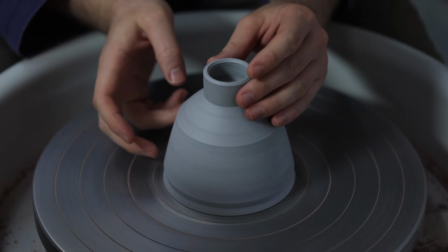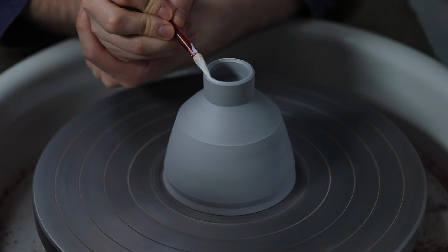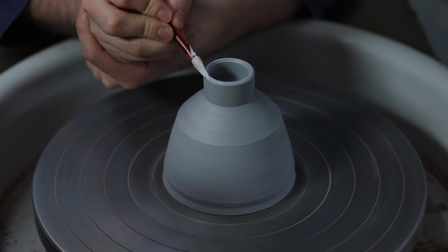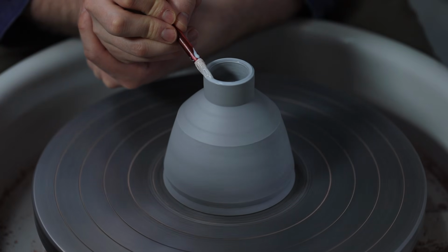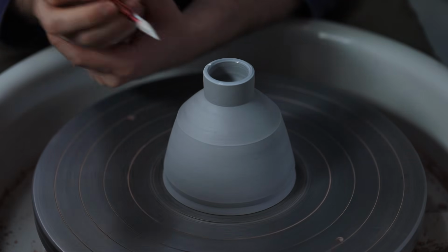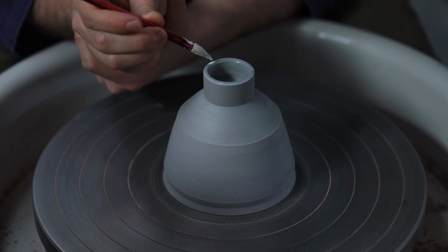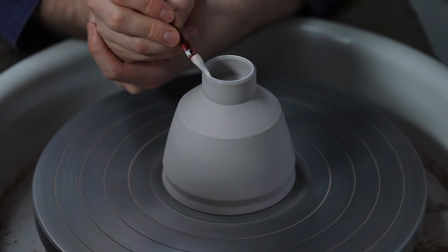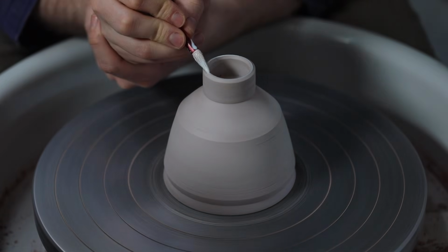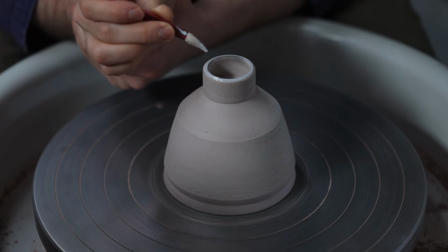As with previous pots made with this glaze, in combination with black clay, when there's a trapped internal space, like this, the glazed surface becomes bubbly and boiled, which is something I think I want to try and avoid. And if the clay does indeed fire black, well, then you shouldn't really be able to tell much of a difference when certain areas of it are left bare.